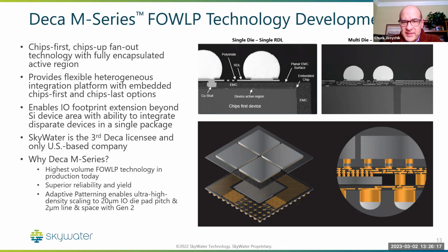the single die, single RDL image in the upper left, or in the center, just shows the basic construction. So you totally encase the die. In the structure, you have a copper stud plated on the die. That allows for a very nice planarization of that epoxy mold compound surface to do the sequential buildup. Of course, this is a simpler design, just showing one layer, and then you can do the UBM and solder bump it.